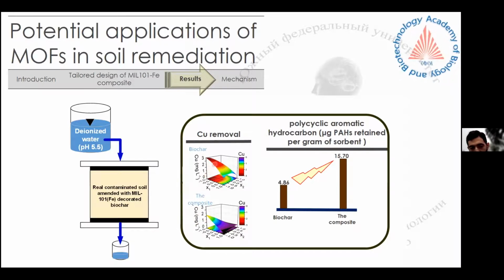And also the trend that you can see here, the trend of the composite has a lower concentration, and it shows that the composite has better performance compared to the biochar. But the result maybe is not interesting in terms of the removal of the heavy metal, but when it comes to the removal of the polycyclic aromatic hydrocarbon, we got a very good result.